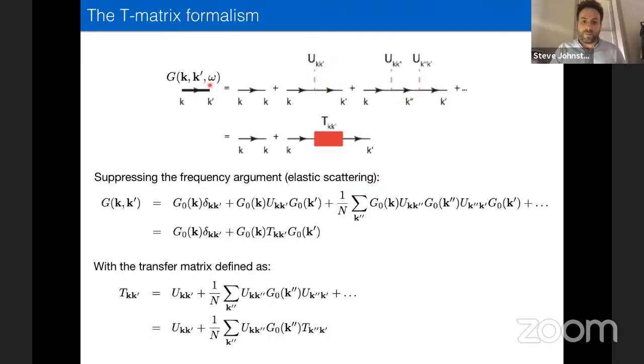The way we do that is with these standard T-matrix formalisms. Again, I'm after a Green's function. And so, like the slit experiment, I have to do coherent sums of all the ways the propagation can occur. I have a term where the electron just propagates from k to k. I have another term where the electron propagates from k to k prime, but interacts with the impurity once, and then I can do that twice, and so forth. Formally, we can resum these into just this free propagator plus the scattering off of an effective potential, which we call the T matrix, which is just the sum of all of these possible scattering processes.